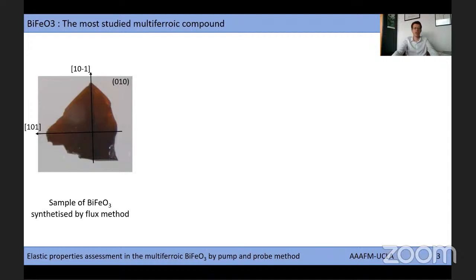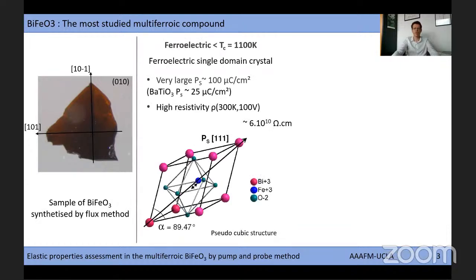So in this study, we have worked on single crystals of one of the best known multiferroics, bismuth ferrite. The single crystals are synthesized by a flux method at Saclay by Dorothée Colson. Bismuth ferrite is ferroelectric below 1100 K with a huge polarization of 100 microcoulombs per square centimeter along the 111 direction of the pseudo-cubic structure. It presents also a high resistivity.